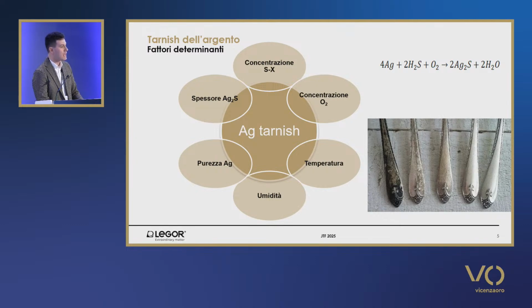Well, there are various reasons for that. Certainly, the concentration of tarnish compounds, which increases the level of tarnishing, thus accelerating the kinetics of the process. And also temperature plays a very important role because temperature itself is a variable which contributes to process kinetics, and then it increases the pressure of sulfur vapor. And humidity, although not present in the reaction, has in fact a very important impact on the tarnish of silver because the absorption of water vapor is the perfect means to accelerate this type of reaction.